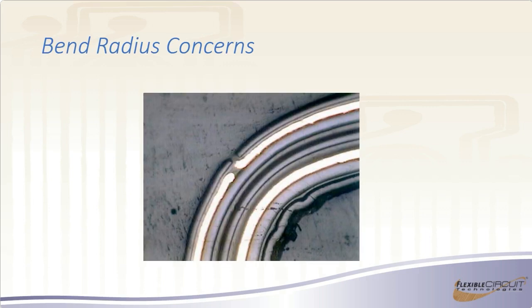Here's what happens when you have excessive tension forces. You can see you have a heavy layer of copper and a heavy layer of polyimide in this area here. Because of that, your neutral bend axis was skewed in, and that ended up causing excessive tension on the outside. And what happened was right here, the polyimide cover cracked, and because of the bond we have between the polyimide cover and the copper, it took the copper with it.